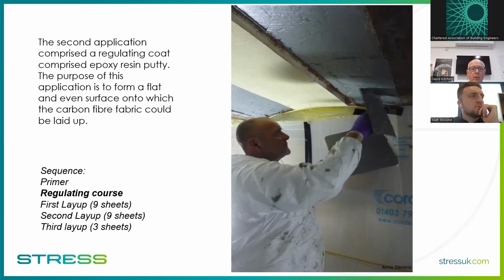And as you will see from that little table on the left, we are actually going to install 21 sheets of carbon fibre. Okay, and why we didn't do it 7-7-7, I've got absolutely no idea. But the idea of doing it in batches is that you're not hanging 9 uncured layers of carbon fibre sheet onto that first bond layer, because obviously gravity is going to try and pull it off the surface as the resin cures. You don't want it to do that, so you keep the volume and weight to a minimum, and 9 sheets was safely fine to do. So we did it in 9-9-3.